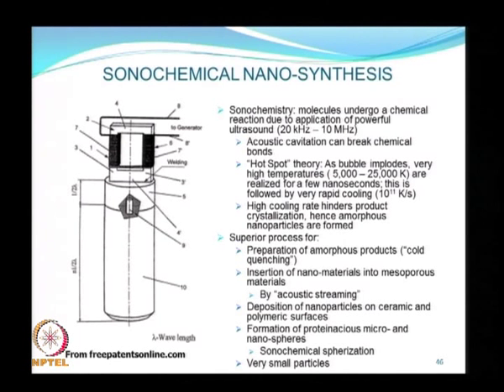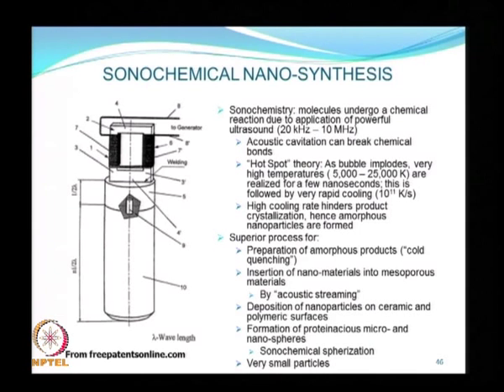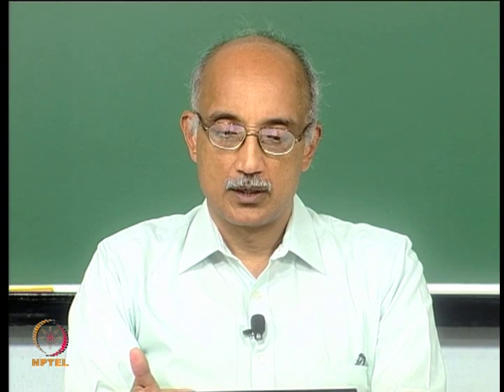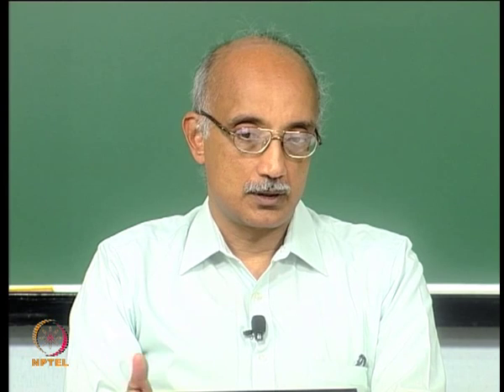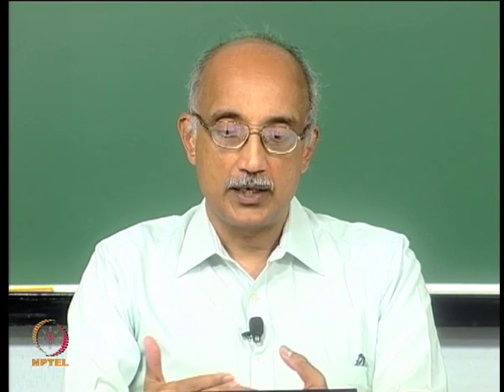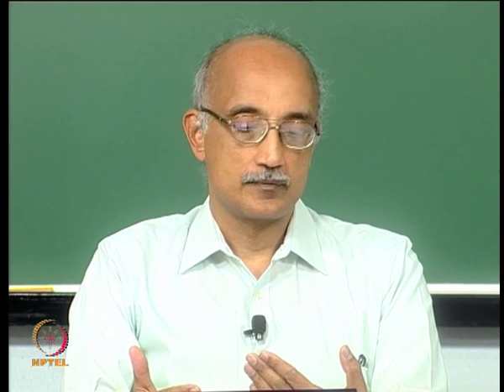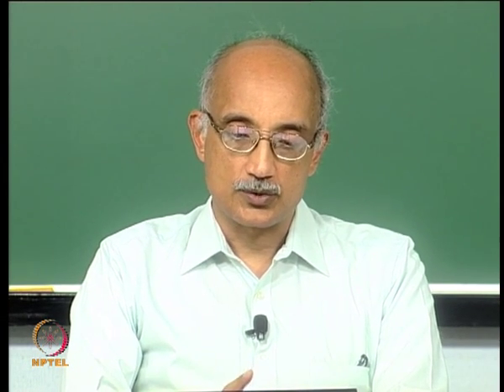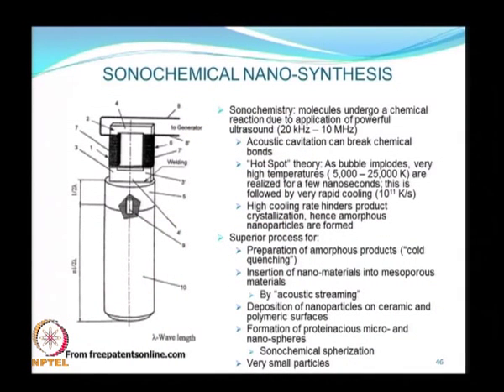The high cooling rate is advantageous in some ways: by quenching the reaction that happens naturally in a cavitation field, you prevent crystallization of the product. This allows amorphous nanoparticles to be made very easily using the sonochemical method. It is therefore considered a superior process for preparation of amorphous nanoparticles because of this cold quenching mechanism.